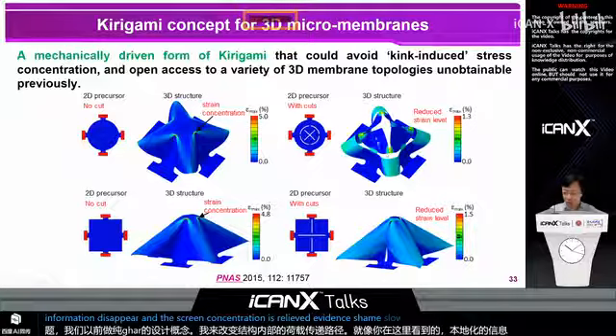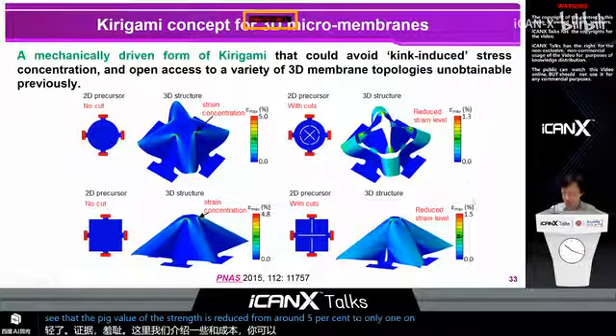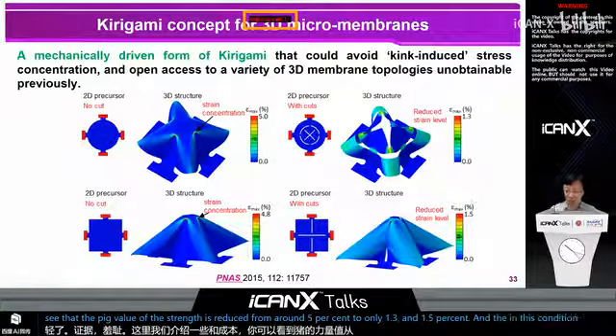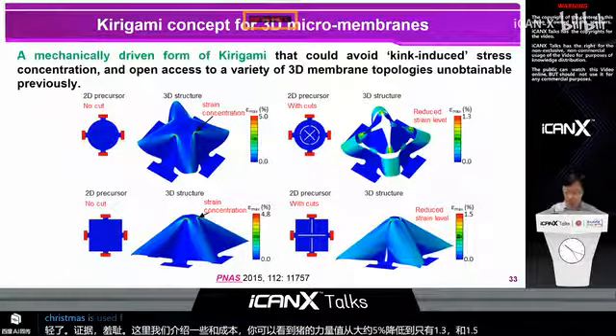So here we introduce some pattern cuts. And you can see that the peak value of the strain is reduced from around 5% to only 1.3 and 1.5%. And in this condition, if single crystal silicon is used for the fabrication, the structure will survive eventually.